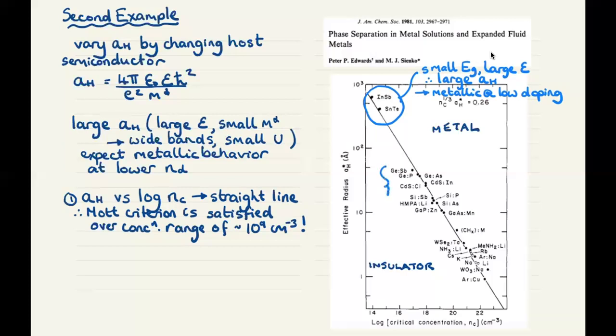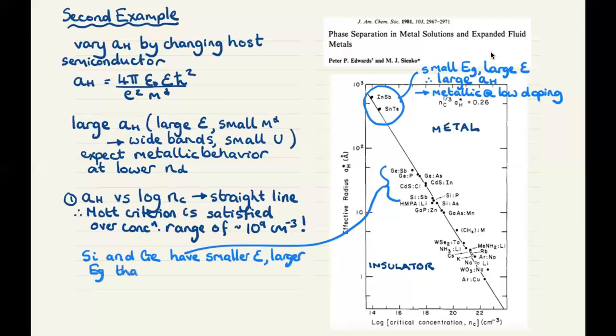Silicon and germanium have smaller dielectric constants than indium antimonide and tin telluride. They're still very covalent semiconductors, but less polarizable than the III-V indium antimonide and tin telluride. They have smaller dielectric constant and slightly larger band gap than indium antimonide and tin telluride. And so they have a smaller effective radius and they become metallic at higher concentration.